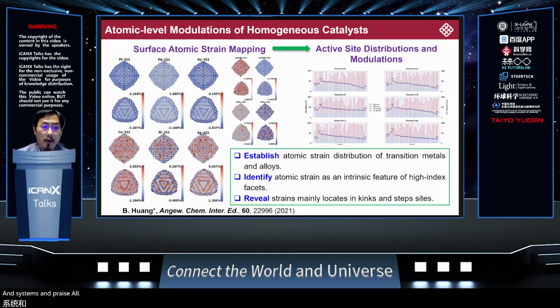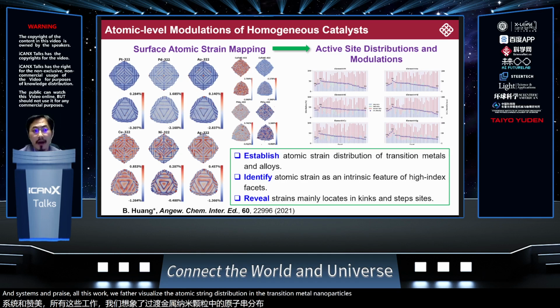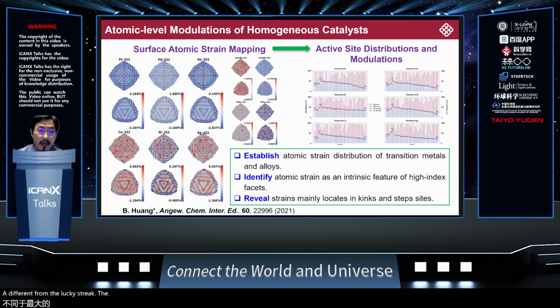And based on this work, we further visualize the atomic strain distribution in late transition metal nanoparticles. Different from the lattice strain, the surface atomic strain is a very interesting intrinsic feature of the nanoparticles. Their distribution and levels are determined by both the elements and the surface structures. Especially the surface steps and kink sites with low coordination numbers show atomic compressive strain. And this visualization technology is a key factor to improve the surface electroactivity predictions. And this work helps us establish the theoretical framework for studying the high index facets for different nanoparticles, which is very important.